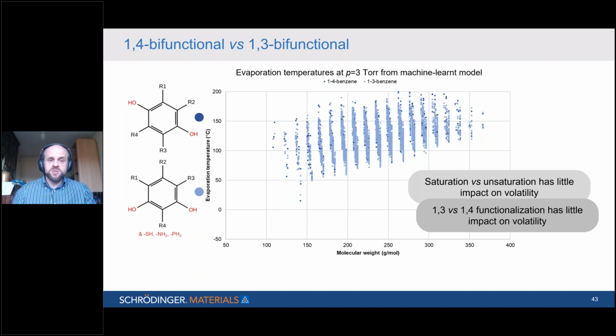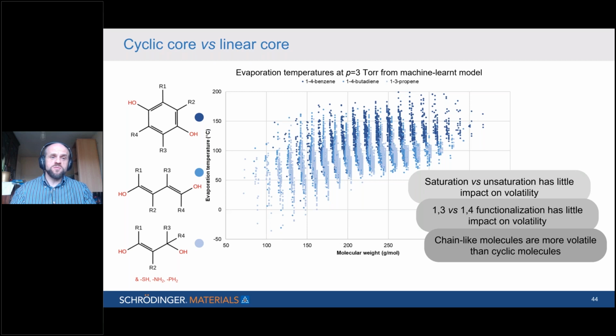But what does change the data quite a bit is opening up the ring, going from the closed benzene ring to the open butadiene or propene. And this does shift the evaporation temperature down a good bit, probably related to the lower rigidity and the higher entropy of the chain-like molecules. And whether that's useful for MLD is an open question at this point, but at least it tells us what's happening with the volatility. So there I've given you an idea of how 50,000 molecules can be quickly assessed for